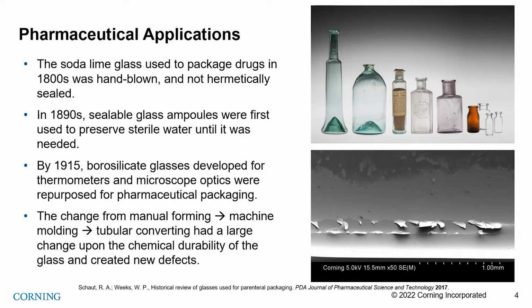And part of the reason that Corning got involved was that there's a long-standing defect here called delamination, that really came to be when the industry shifted from manual forming or kind of flame working or blowing to more machine forming on a turret type machine, where you're going from tube to the vial shape. And specifically what you're looking at in the image in the lower right are flakes of the glass surface that are spalling off and could have entered the drug product. And so being able to understand the origins of this defect and then coming up with a way to address it and prevent it from happening was key. Next slide, please.